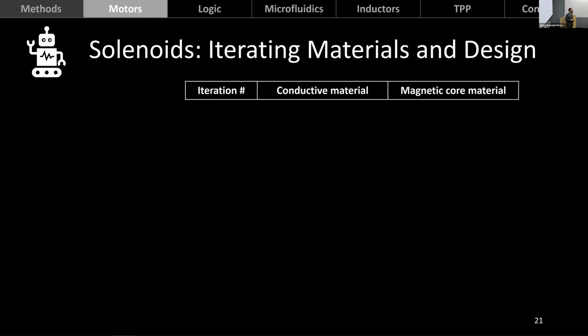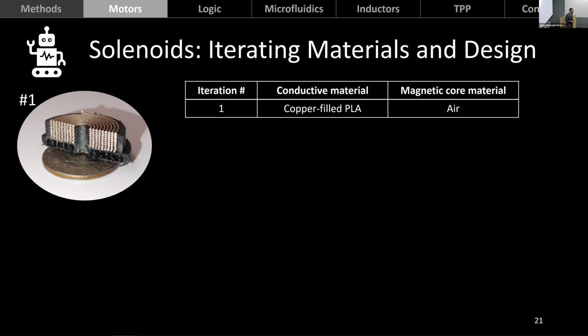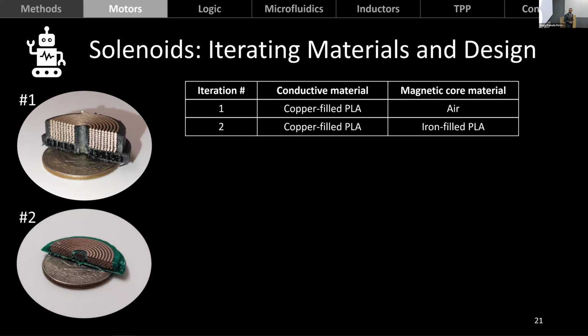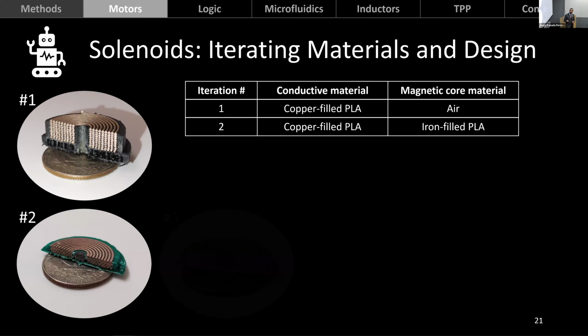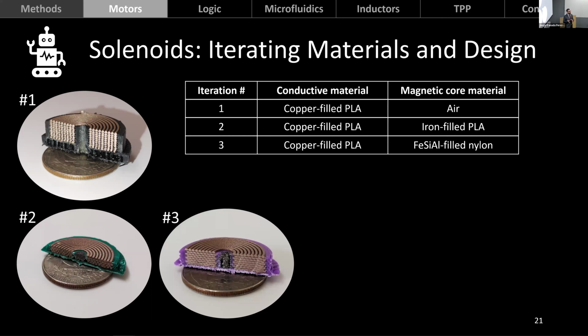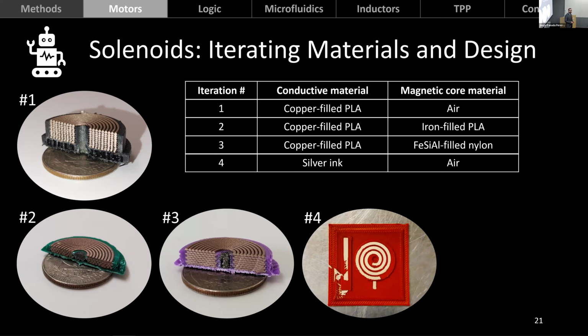And we did a few different iterations as we became able to use higher performing materials, always with the objective in mind of generating higher, stronger magnetic fields. In the first iteration, we used the copper filled PLA filament, which I mentioned earlier, and no material for the core, or an air core. In the second iteration, we used the same conductive material, but we introduced a magnetic core using the iron filled PLA filament that I also introduced earlier. In the next iteration, we swapped that filament for the higher performing pellets-based material that we printed the cores from. And later we introduced silver ink. So we swapped the conductive filament for silver ink, and we printed those both with an air core and with a magnetic core.